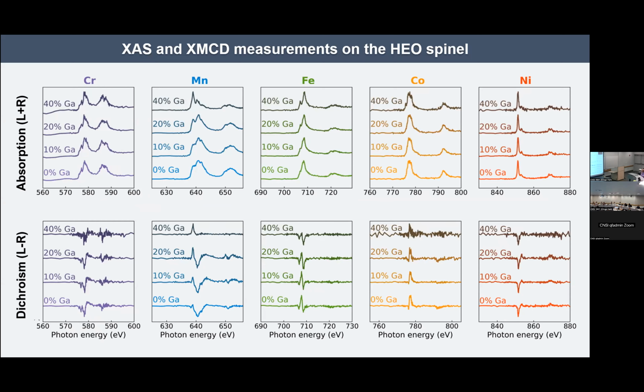Okay, so this is the entirety of the data that we collected in our first set of X-ray absorption experiments. You can kind of let your eyes soften because I'm not expecting you to take anything away from this slide other than we have a lot of data. The way the data here is structured is we have 4 compositions, 0, 10, 20, and 40% gallium. We have 5 elements, and notice that each of these elements are measured in non-overlapping energy windows. There's no overlap or contamination of the spectra from chromium and manganese. They're very well defined from one another.